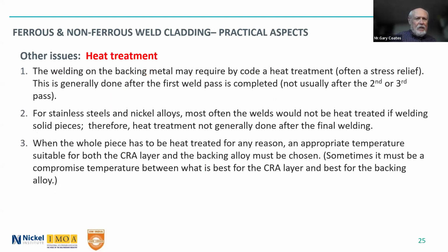So, heat treatment, and I saw there was a question in the Q&A already about this. You don't usually need any sort of heat treatment for the stainless steel or the nickel alloy, but you may need it by code for the backing material. And it's often a stress relief kind of material, especially for oil and gas, or maybe when you have hydrogen sulfide there. So often it is done after the first pass is completed. So you do one pass, and then you do the stress relief, and then you do the other 1 or 2 passes after that of weld overlay. You don't need to do a heat treatment by code after that.